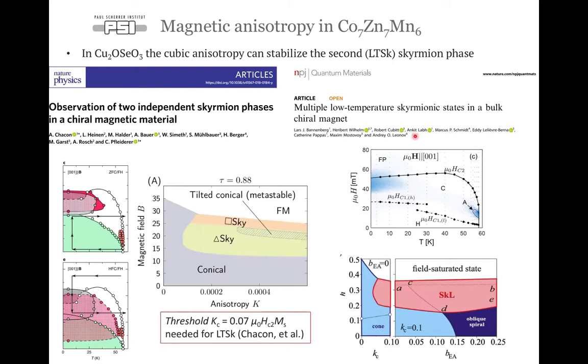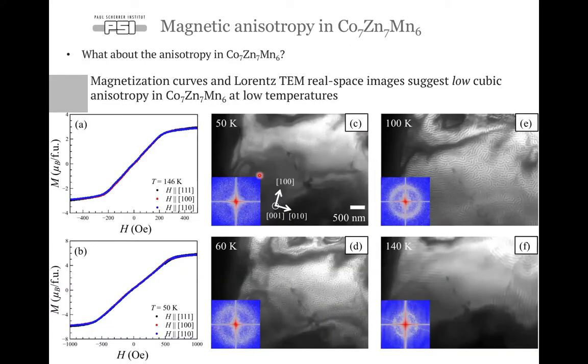Another important note: I have already mentioned that previously the low temperature Skyrmion lattice was also observed in Cu2OSeO3 single crystals, and it was explained by the development of the cubic anisotropy at low temperatures. And there are even theoretical proposals for the magnitude of the cubic anisotropy constant that is needed to stabilize the low temperature Skyrmion lattice by this simple formula. So what about the magnetic anisotropy in Co7Zn7Mn6 single crystals?